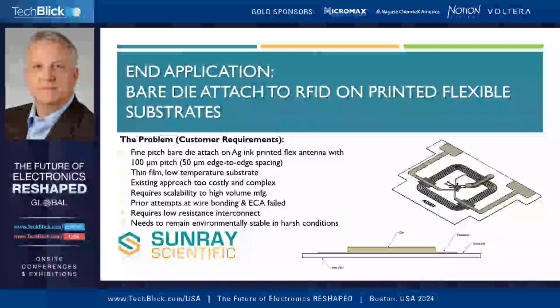And the problem that they were having was it's a very fine pitch die. So basically 45 to 50 microns edge to edge that they had to attach to this printed flexible antenna. Thin film with low temperature substrate, 2 mil polyester, can be tricky to bond materials to as well as to print on. So very low profile material. Existing approach was very costly and complex. It required scalability into high volume.